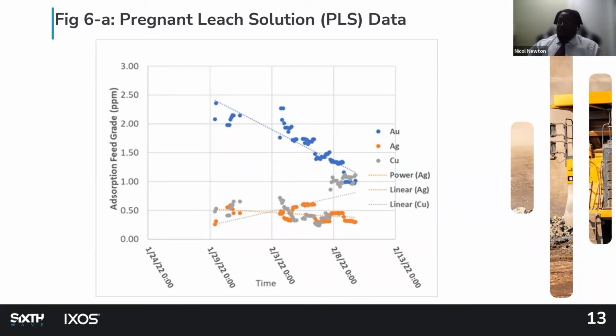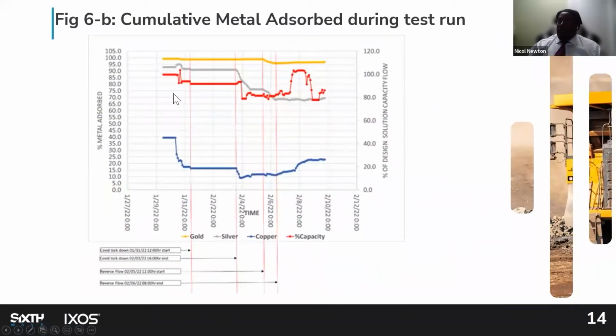So what was happening was that all the gold first leached out, followed by the silver, and then the copper. So towards the end, we had more copper in the solution, and then we had less gold in the solution. In other words, if we had that circuit in place, we'll be in a position to recover all the gold and then all the silver, followed by all the copper. This is the cumulative metal absorption that we trended over the period that we were on site.